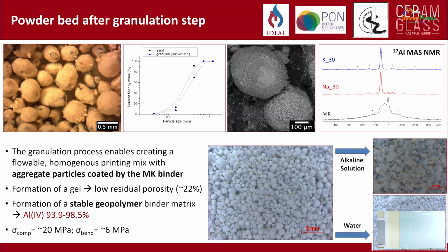And we demonstrated that using aluminum solid state NMR spectroscopy. And you can see that these are the characteristic peaks for the metakaolin, where aluminum is sixfold coordinated. So it's not part of the network in this form, but after reaction, it becomes fourfold coordinated, meaning that it becomes part of the 3D continuous geopolymer network. So the full geopolymerization has occurred.